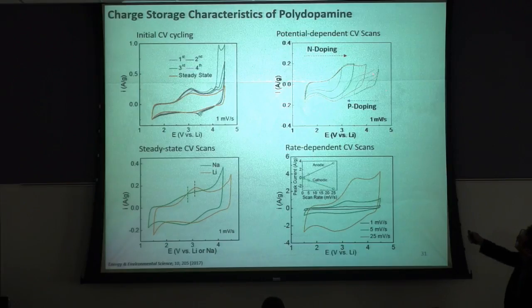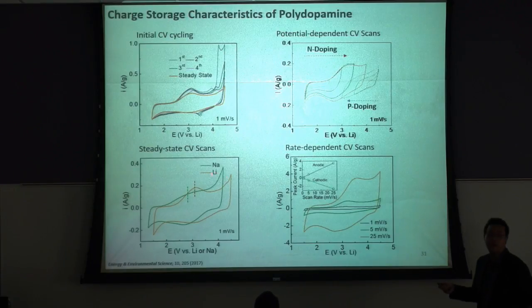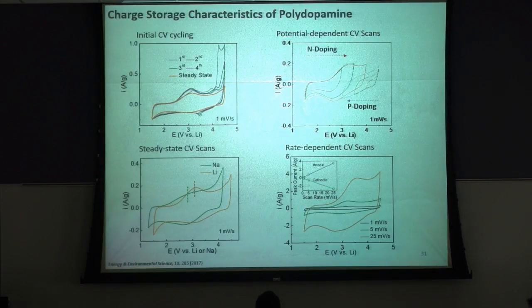Interestingly, we can also see some development of a redox feature here at the high potential region around 4 volts. We believe this comes from the p-doping process of the polydopamine. I will show some mechanism for this in the next slide. This polydopamine is redox active not only with the lithium ion, but also with the sodium ion. So we can use this for both lithium-ion batteries and sodium-ion batteries. Also, this polydopamine film shows good rate performance by maintaining its redox feature up to 25 millivolts per second.